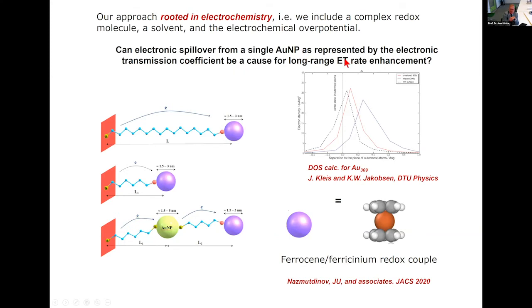Electron spillover means that at a metallic surface, there is a certain spillover of electronic density. A metallic electrode surface is not just a hard wall. There's a smooth change in electron density from the bulk of the metal to zero sufficiently far away from the metallic surface. If that is different for a metallic nanoparticle from a metallic surface, then there could be an inherent catalytic effect. And some data done here at DTU Physics many years ago show that there could be some effect like that. This is the planar gold surface, and this is the metallic nanoparticle. In this case, it is a 309 atom nanoparticle. So it is as if the electronic density expands, and it would expand more the more negatively charged the surface.